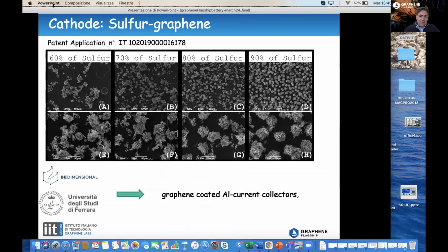And an additional activity is led by Jusef Hassoun at the University of Ferrara, and our group is on the development of graphene sulfur composite. You can see some pictures of graphene sulfur composite particles with different content of sulfur, and also on the development of coatings for aluminum collectors.